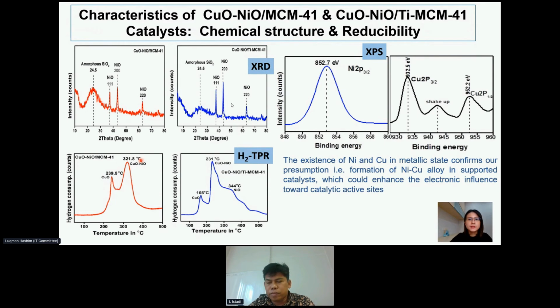So besides, there is an extra peak that is present for nickel oxide reduction, which is due to the presence of the interactions between the nickel with the titanium MCM41 support. So it leads to another new active site for the reduction process. So based on the XPS analysis, the existence of this nickel and also the copper in the bimetallic state confirms the formation of these nickel copper alloys in the supported catalyst, and this can help to enhance the synergistic effects towards the deoxygenation process.